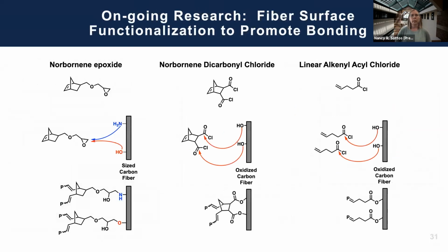Also ongoing, and again, I'll just mention this because we're doing a lot of testing, and it is a challenging problem. We have been working on functionalizing the fiber surface in order to optimize the bonding of the DCPD to commercially available fibers. And we've looked at several different fiber surface treatments. Initially, this norbornene dicarbonyl chloride is perhaps the most promising, and basically ongoing work, as we characterize the interface over a large number of samples and work to scale that up to our woven composites.